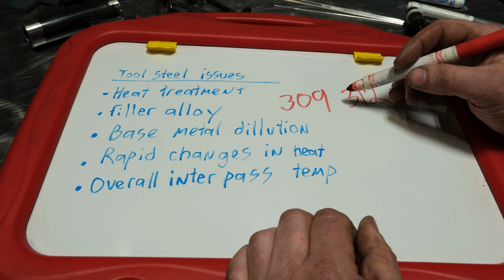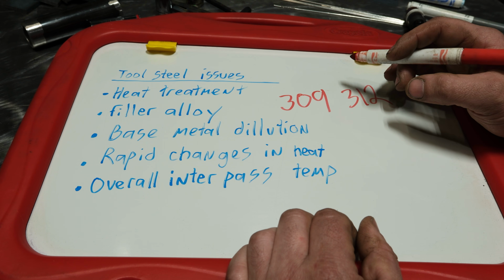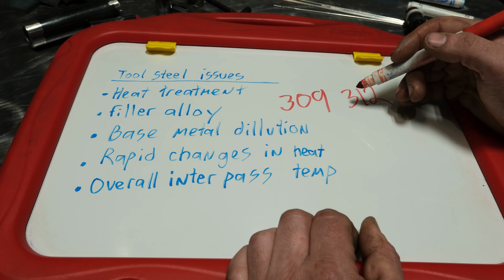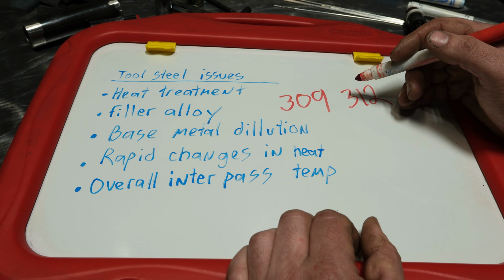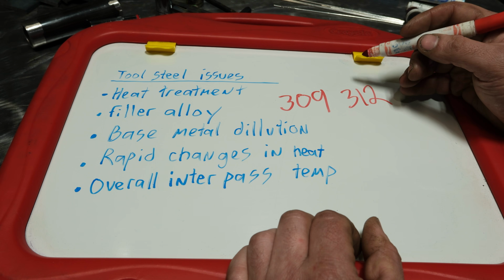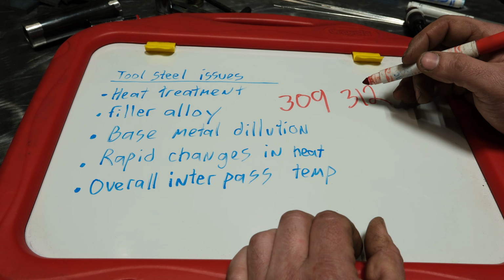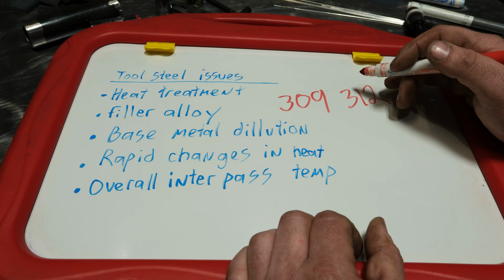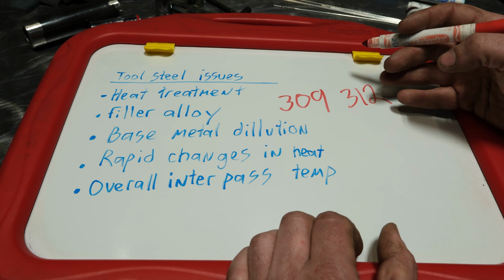Now, technically, a lot of your chrome vanadium steels tend to be welded with ER80, which is basically chromoly. That can commonly be used. The problem that I have with using that and recommending that to you guys at home is that the chromoly filler tends to produce a very brittle weld, and you get rid of that via heat treatment. Well, the problem is you're not going to be heat treating these more than likely. Therefore, by sticking with that over even ER70 standard TIG wire will probably make a more ductile weld on, say, a chrome socket than chromoly filler will. So my recommendation is to stay away from higher strength fillers and stick with ER70, which again, I would not recommend, but if that's all you have access to, generally it will work okay. The weld will probably be far more brittle than both 309 and 312 stainless. So 100% my recommendation is if you can get one of these, use one of those.